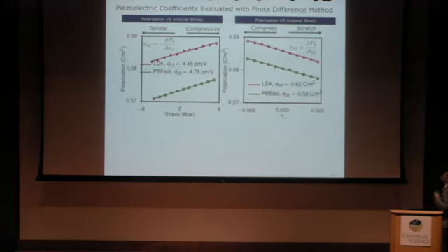We also evaluate the piezoelectric coefficients with the finite difference method, which I think is probably much more intuitive than density functional perturbation theory. These are the results for lithium beryllium antimony. What I did is to look at the polarization as a function of uniaxial stress and also the polarization as a function of uniaxial strain. With the two, they essentially give the same results. The slope tells us the piezoelectric coefficients. So I think this figure is probably more intuitive.